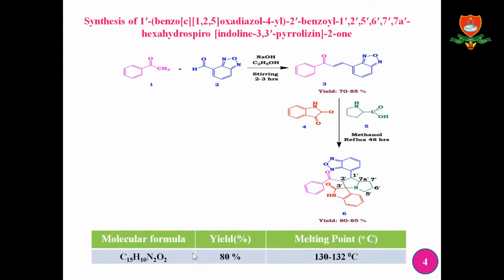A mixture of acetophenone and benzo[c][1,2,5]oxadiazole-4-carbaldehyde is reacted in the presence of sodium hydroxide and ethanol to give chalcone. In the second step, chalcone reacts with isatin and proline in methanol medium, refluxed for 48 hours. The reaction mixture was monitored by TLC. The product was extracted using ethyl acetate, dried, and recrystallized using acetonitrile. It gives an excellent yield, that is 80 to 85%. Its molecular formula is C15H10N2O2. Its melting point is 130 to 132 degrees Celsius.